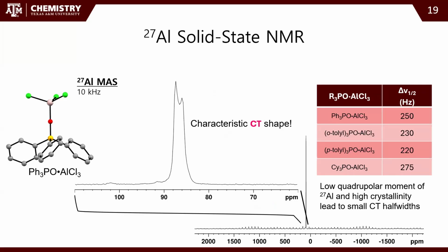So the triphenylphosphine has the largest span of over 4,000 ppm. And it also has a really interesting shape, which is characteristic for a quadrupolar nucleus. So a lot of quadrupolar spectra have these interesting central transition shapes that kind of look like a lopsided Batman. But the rest of these have reduced spans, and they kind of have a Gaussian-Lorentzian central transition. So that's telling us these triphenylphosphines have the largest quadrupolar interactions and the least symmetric electric field gradient, right? We didn't look into analyzing this too much because it's only like 7 data points. So it's kind of limited data that we could get from that.